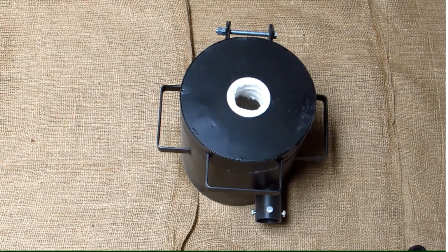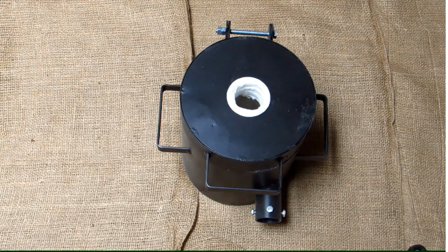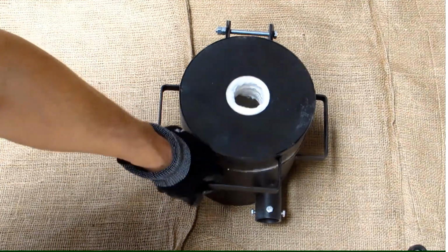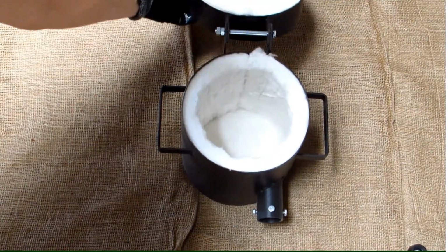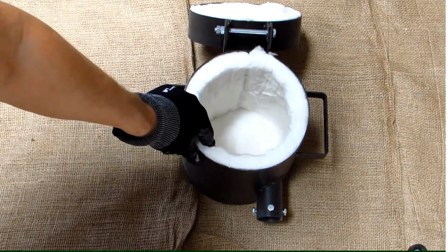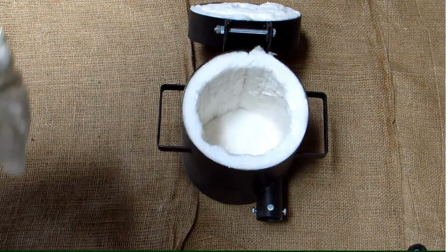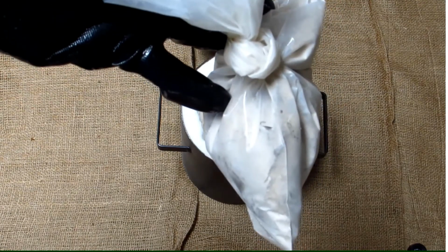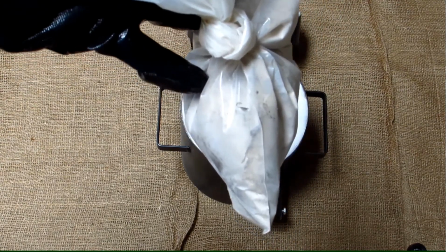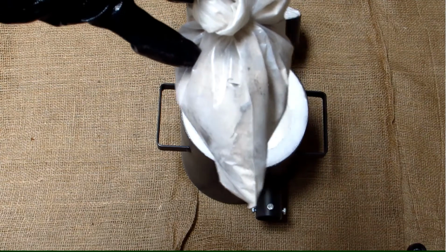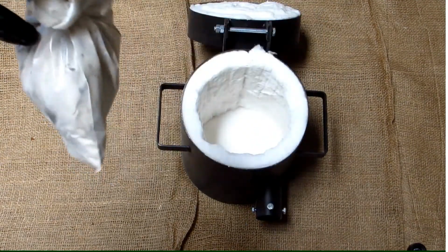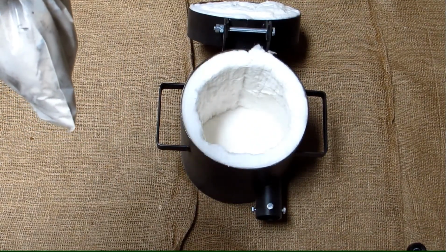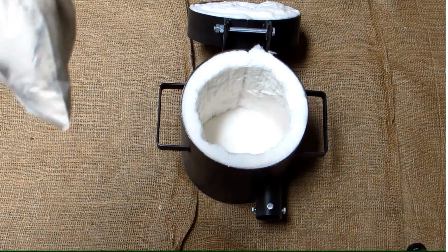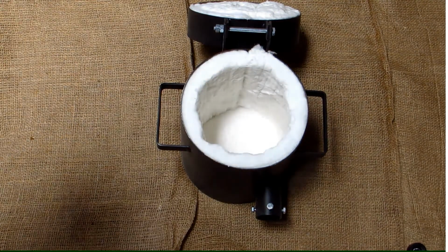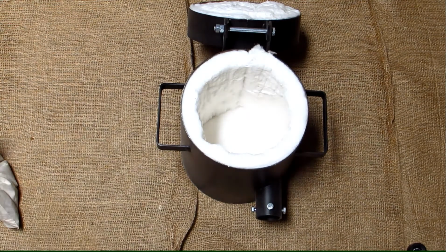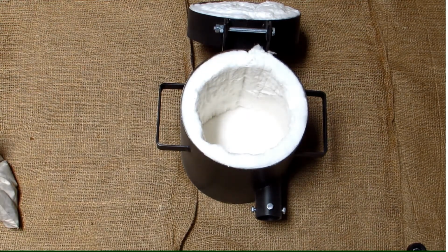Here's the furnace straight out of the box. As you can see, it's kind of small. The furnace comes lined with a ceramic wool liner, and it's pretty soft. There's some problems with the ceramic wool liner, with the ceramic particles aerating, so the furnace comes with this bag of mortar. I didn't like the idea of coating the furnace with mortar because you're putting something hard on something soft, and that can cause some problems because the mortar will just kind of break off.